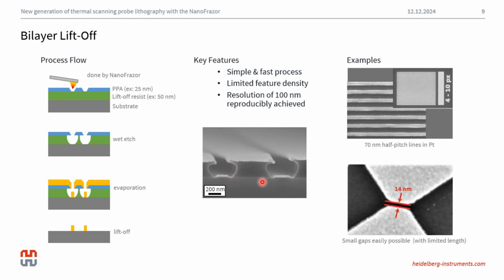So when it comes to high density features, there's a limit beyond which you cannot make these two lines approach each other. And this is because of the isotropic undercut of the underlayer. If we were to make these lines any closer, you could imagine how the top layer would collapse. So with this method, we've been able to reproducibly achieve resolutions when it comes to line and spaces that are in the 100 nanometer range. And for isolated features, this can be a much higher resolution.